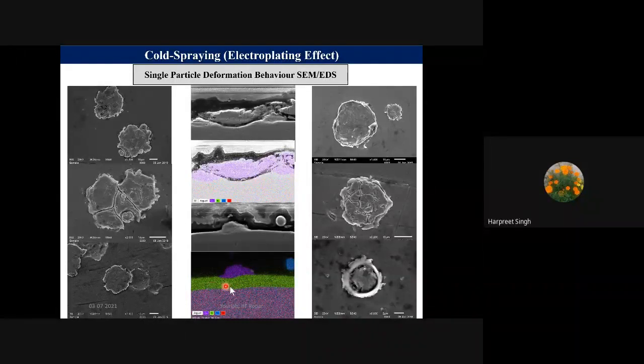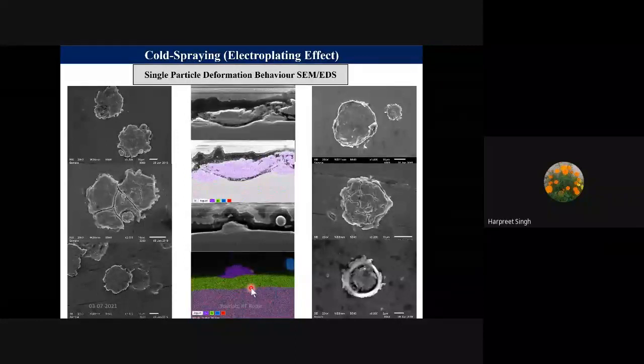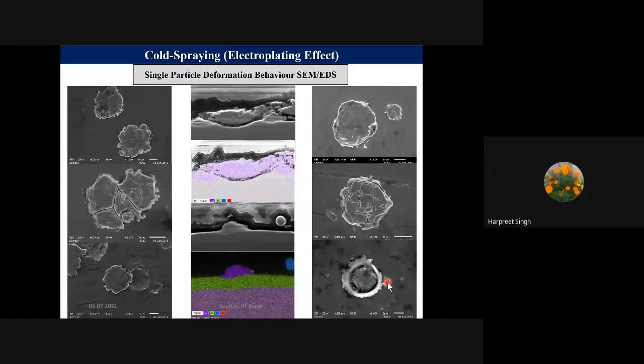So nickel could sustain here nicely and could host this copper nicely without getting deformed much. And this is referring to this one. Okay. So that is where we have concluded that even the copper interlayer was not helping us, but the nickel interlayer helped us to host these subsequent layers of copper on this whole system.